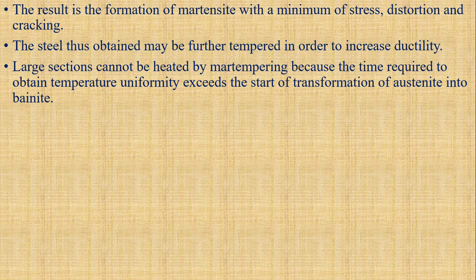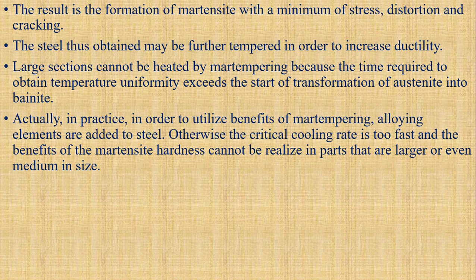Large sections cannot be treated by martempering because the time required to obtain temperature uniformity exceeds the start of the transformation of austenite into bainite. Actually, in practice, in order to utilize the benefits of martempering, alloying elements are added to steel. Otherwise, the critical cooling rate is too fast and the benefits of martensite hardness cannot be realized in parts that are larger or even medium in size. Thank you.